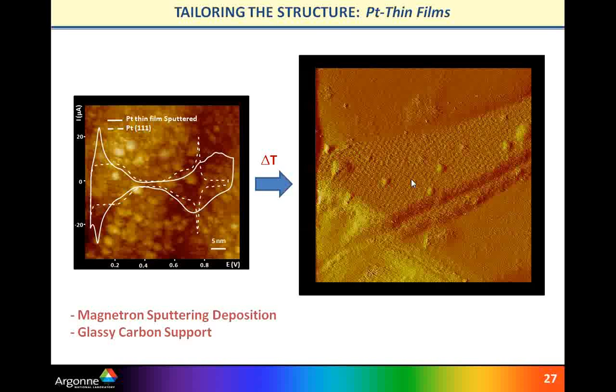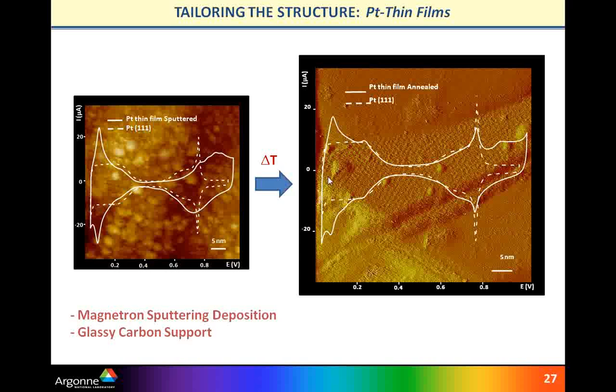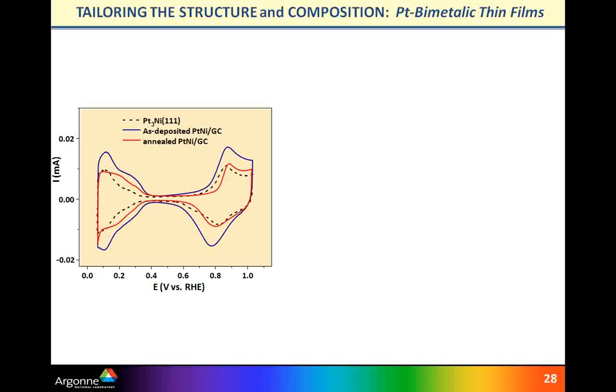But after careful annealing, we could actually see the appearance of single crystalline facets. More importantly, the entire surface gave us feedback of a more or less single crystalline type of surface, which nicely distinguished the butterfly region, which is a fingerprint property of the platinum 111 surface in perchloric acid. So we were amazed that after careful treatment, we could indeed tune not only the composition, but also the structure.